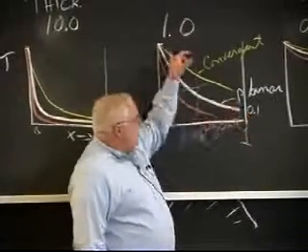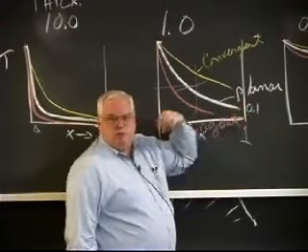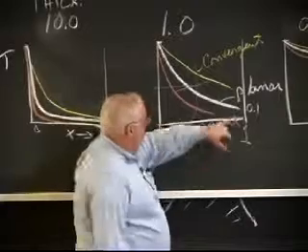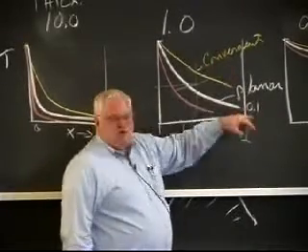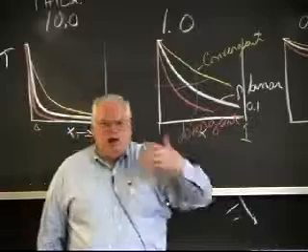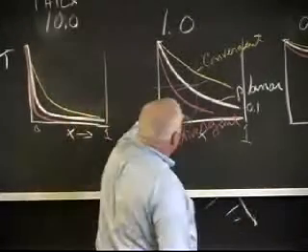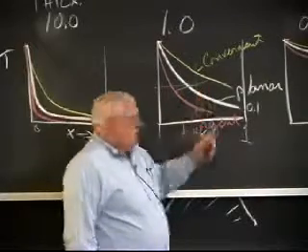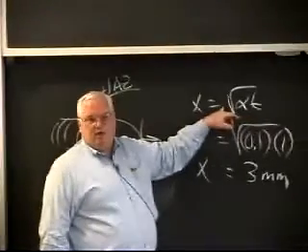I just said that at a 3 millimeter distance in a piece of steel, at that particular travel speed, with a 1 centimeter long weld pool, I would have dropped my temperature by 90%. Well, 90% is not my heat effective zone size. Maybe about 50% of the heat is my heat effective zone size.